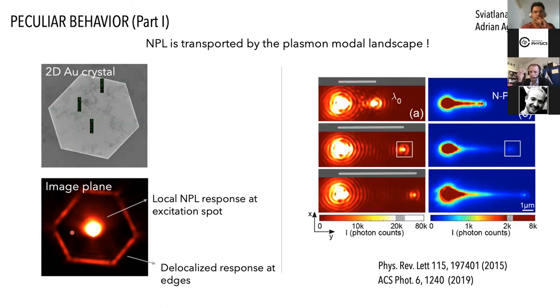So the vector which mediates this non-locality is actually the surface plasmon modal landscape. So if you have a surface plasmon in the system and you are exciting with your laser, then you will have a distribution of plasmons in this 2D structure. Of course, you have a very complex pattern, but that complex pattern is basically sucking up the laser energy, and it's going to be a pump, also a femtosecond plasmon that is distributed around the structure, and which will create locally all these nonlinearities that are bringing the electron gas to elevated temperature, and then that creates substantially this secondary emission seen as NPL. So this is seen here in this 2D structure, but it's a little bit more obvious here in this